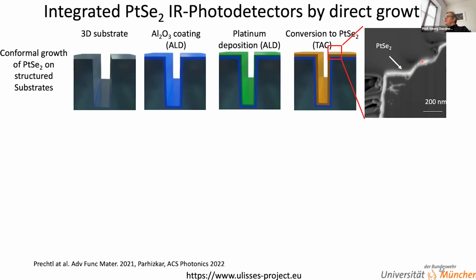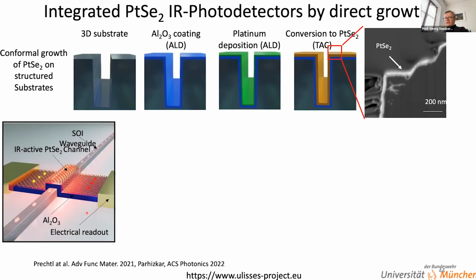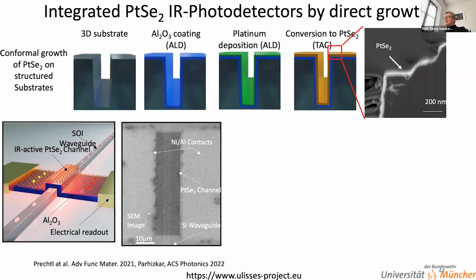Here's a cross-sectional image of platinum grown in the trench structures near the corner, and you can see that we have a conformal coating of these materials. We actually managed to integrate IR active PtSe2 channels on silicon waveguides directly. This is a schematic, and that's a real image. You see the waveguide here, and the gray region is basically our PtSe2 photodetector on top of the channel.